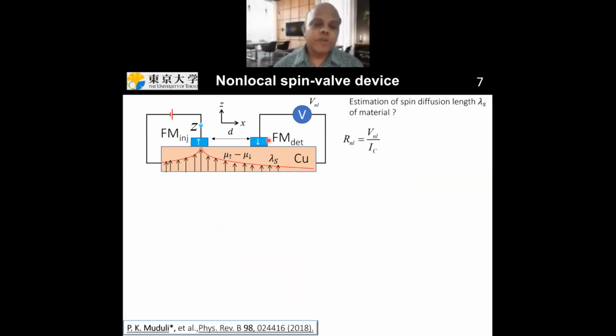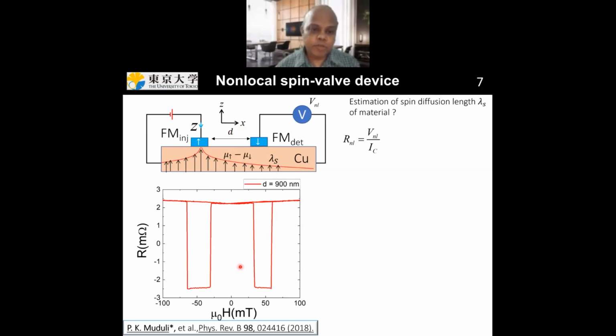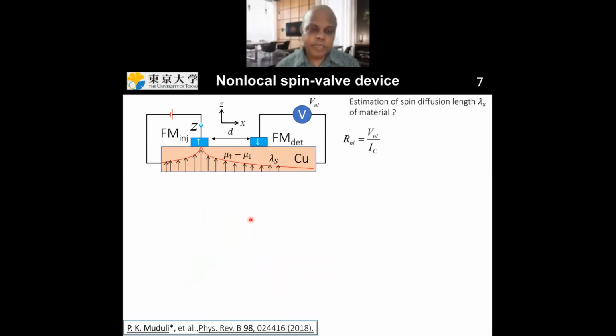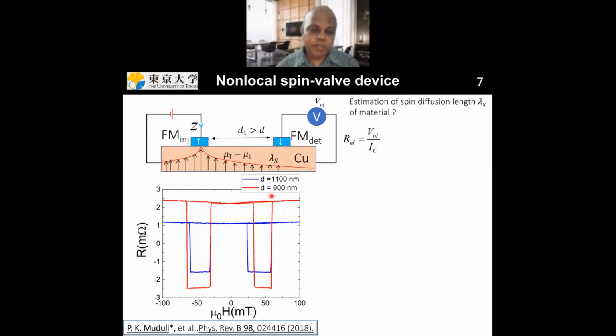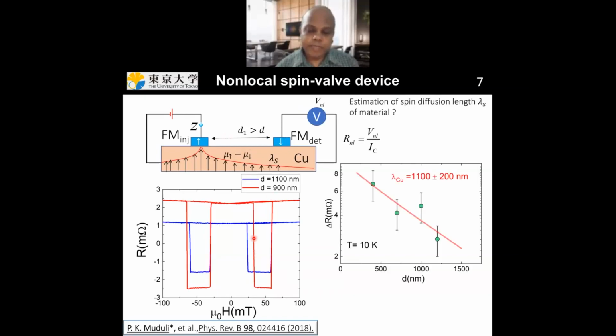This kind of device can be used to measure the spin diffusion length of materials. As you know, spin diffusion length is a characteristic length which defines how far a spin current can travel inside a material. You can intuitively guess that if you vary the injector and detector separation and measure how far you can measure the non-local voltage, that will give you an idea of the spin diffusion length of the material. Suppose your distance is d and you measure the spin signal, it will look something like this. Now if you increase the distance slightly, you will see that your spin signal is reduced. So if you make many devices in which you vary the distance between injector and detector and plot the spin signal, you will see that it decreases exponentially.